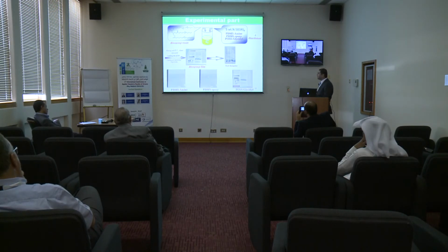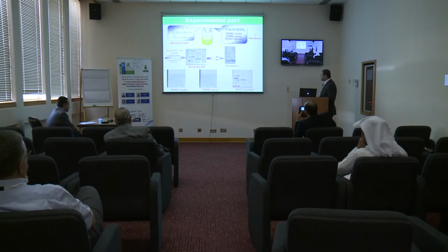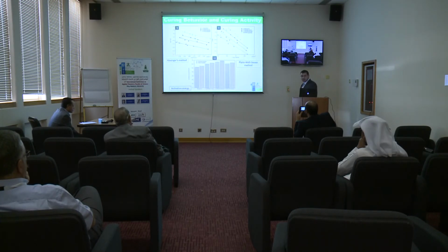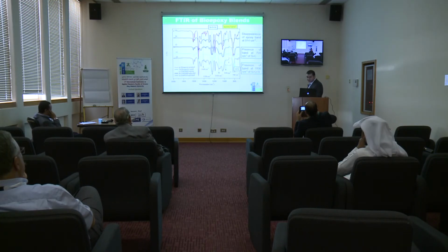We found that the amine-terminated polydimethyl siloxane with bio-epoxy and the epoxy-terminated one gave an opaque film. However, using POSS-glycidyl gave a transparent film. We also calculated the activation energy of these products, and found that the activation energy increased compared to the neat bio-epoxy.